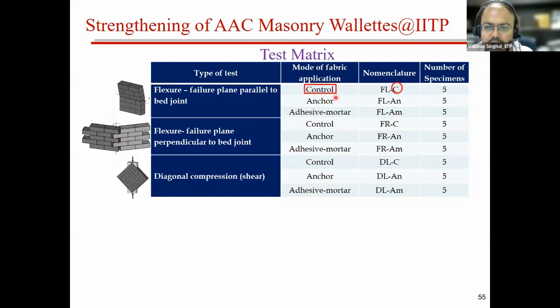So we had some control specimens where no strengthening was used, and there were 2 types of strengthening technique we have adopted. The first one is having anchors, where the fabric, to avoid debonding, has been attached to the surface also by using anchors. In the next case, we have used adhesive mortar, thinking that it will provide better bonding. Adhesive mortar is nothing but the mortar which we commonly use for laying the AAC block. You might have seen this adhesive mortar given by various companies like Ultratech and other companies. Sometimes they call it a polymer mortar also. And for each case, we have five specimens.